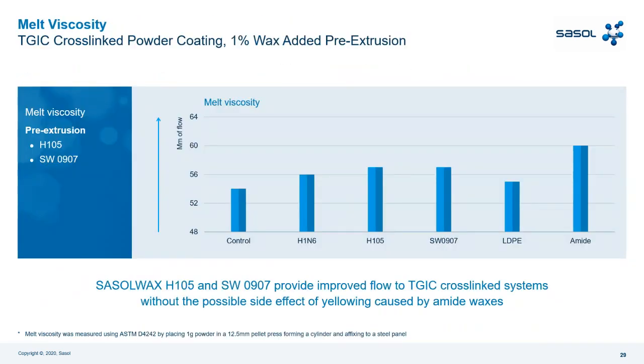Melt viscosity is important. The melt viscosity you didn't see with the other technology. With the TGIC it is important, always at 1%. You see the control that has a low value. In this case, you need to check the highest value. So Sasol Wax H105, that is the coarse powder, achieves the best results together with Sasol Wax 0907, that is the microcrystalline wax in pastillized form. So you can see that they improve the melt viscosity, so improve in this case the viscosity.